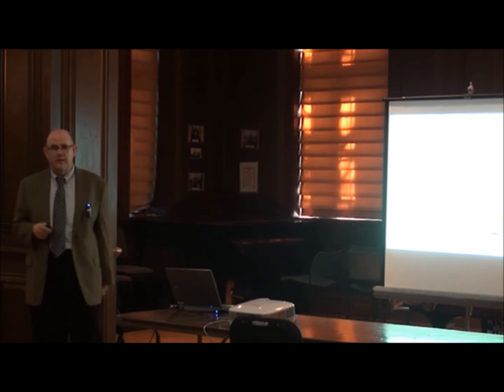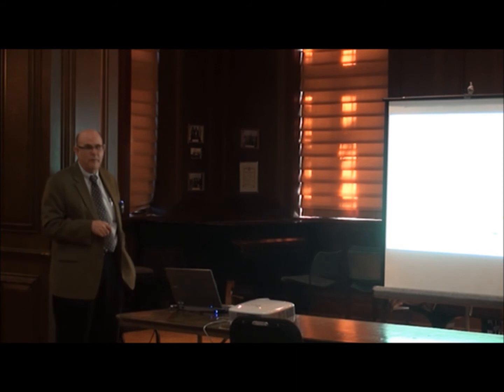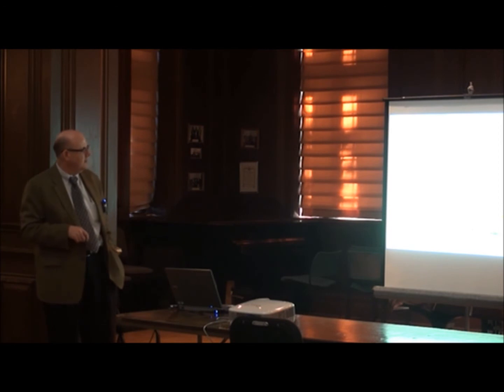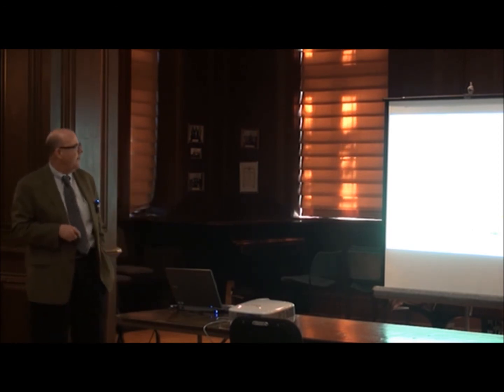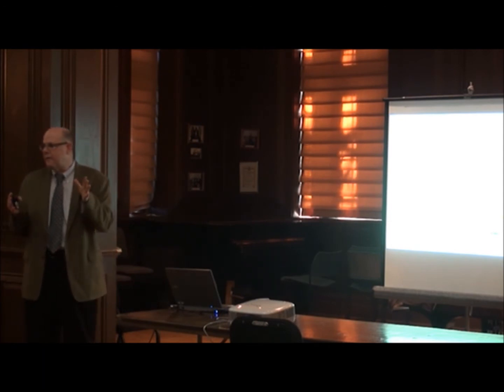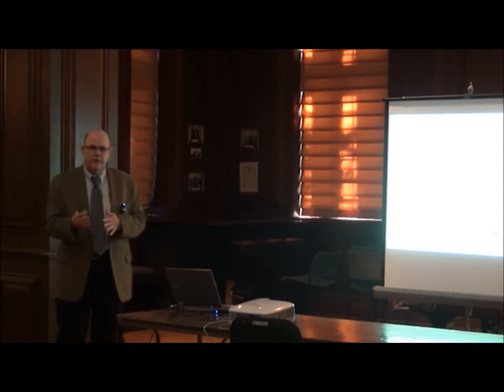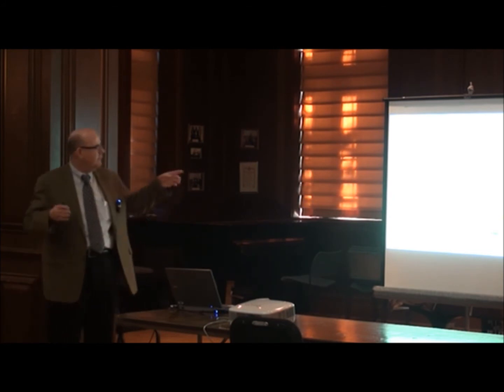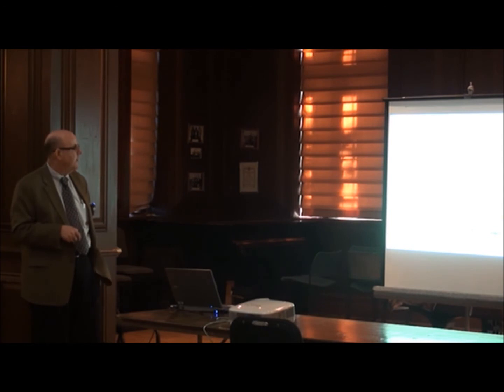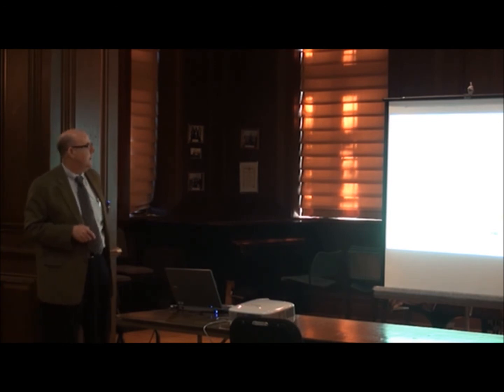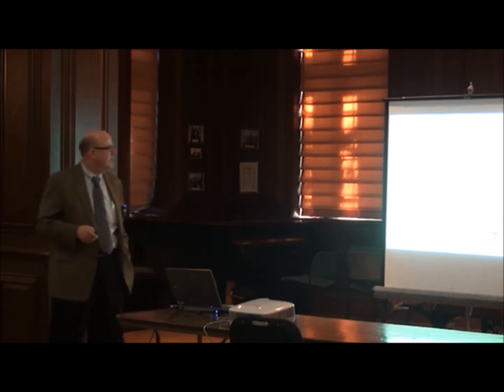Unless the asperities are touching, then it's a whole other story. So what we talk about is the idea that there's a fluid film built up between two surfaces, and the minimum film thickness relative to the composite roughness of the two surfaces as defined here, that ratio is what we call the lambda ratio. So the ratio of this minimum separation over the composite RMS roughness. If this is a large number, greater than 3, 4, 6, that kind of thing, then the surfaces are generally really separated. The asperities aren't touching across that interface. And as a result, the friction is really just coming from the shearing of the fluids. As that lambda ratio gets smaller, so either the surface gets smoother, the film gets thinner, or the surface gets rougher, then we might get asperity contact across the interface and we get some friction that way.